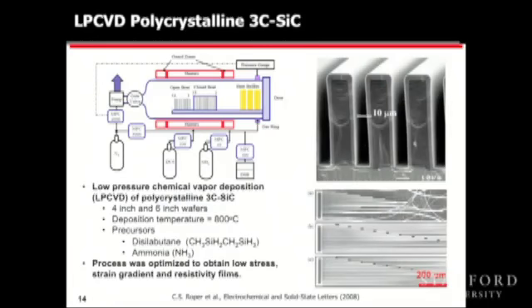This is an image of a low pressure chemical vapor deposition system that's used to deposit polycrystalline silicon carbide. We have these here over in the Stanford Nanofabrication Facility, and these are commercial-based systems that are also used in the semiconductor industry to deposit materials that would, again, be found in your cell phone or your laptops. This is an image of a thin film of silicon carbide that's conformally coated on silicon trenches. This can be done on 4-inch or 6-inch substrates.